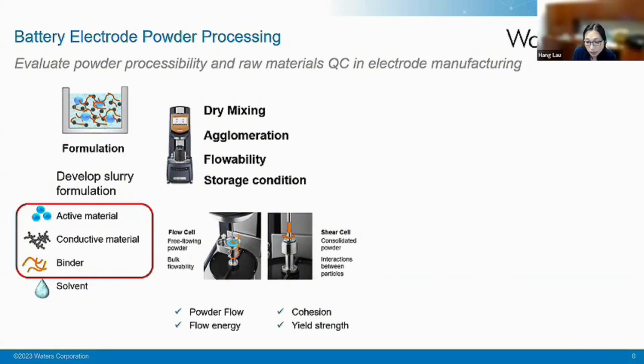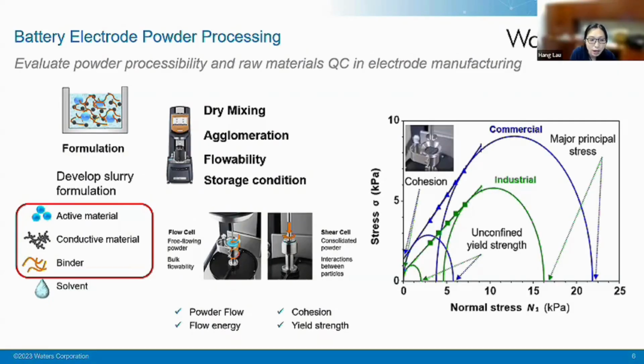Would they be more willing, or easier, to adhere? One example that we have put in here is two types of graphite material. You see that they have very different cohesion and very different yield strength. Cohesion will give you information on how easily those particles will agglomerate and stick together. Cohesion depends on the storage condition that the powder is kept in. Sometimes the coating will impact the cohesion property.